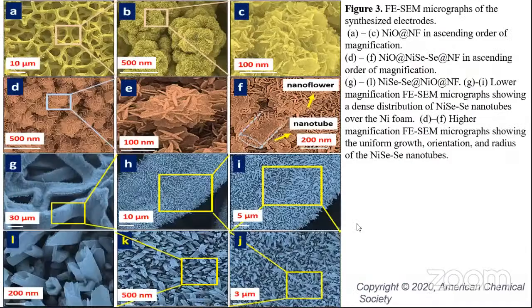Now, coming to the FESEM micrographs, what we have seen for sample A, which is the pure sample, is nickel oxide nanoflowers grown over the surface of the current collector. We saw a nanoflower-like morphology. In the figure, D, E, and F correspond to the second electrode, in which we have grown nickel oxide nanoflowers over the nickel selenide nanotubes. Here also you can see the morphology was retained, and figures G to J show the nickel selenide nanotubes which have been grown on nickel oxide nanoflowers. So here there's a reversal in the hierarchy.